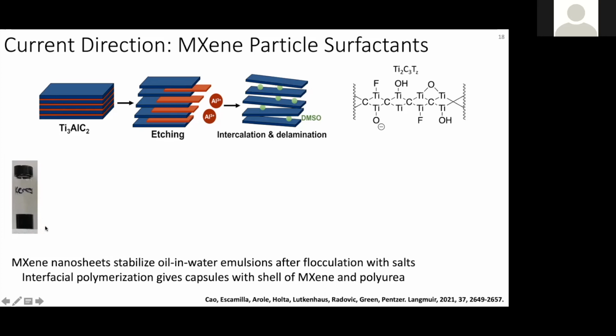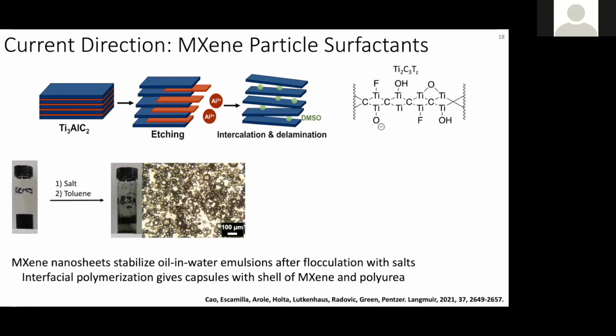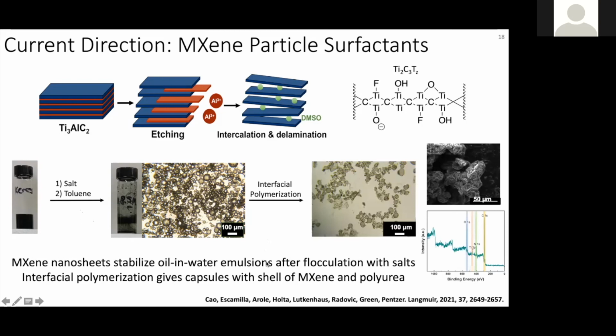They're dispersible in water. And so we just took a page out of the clay playbook from a few decades ago and just added in salts such as sodium chloride, which flocculates the nanosheets, so overcomes the repulsion between the negatively charged nanosheets. We then add in toluene in this case and agitate, and we access our emulsions that are stabilized by the salt flocculated MXenes. And we can use the same interfacial polymerization I talked about with the GO nanosheets to make capsules.